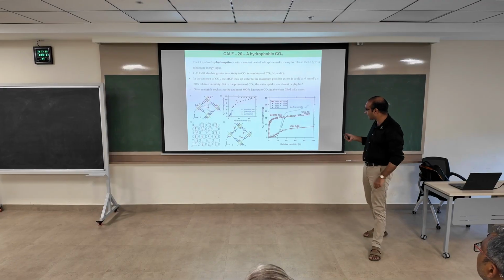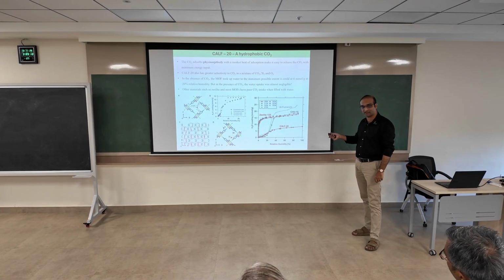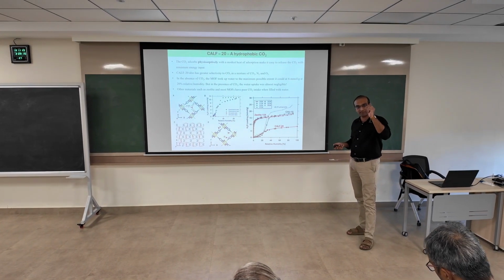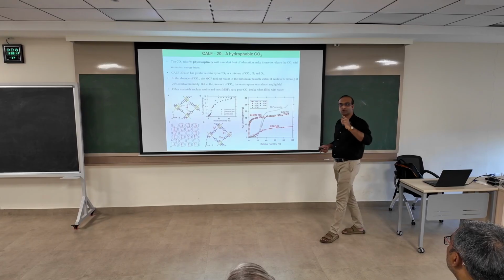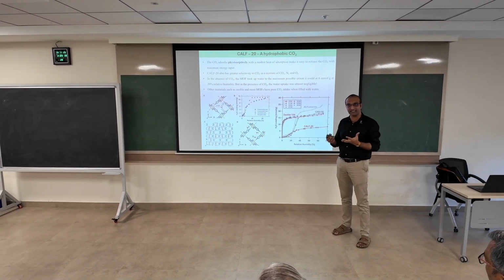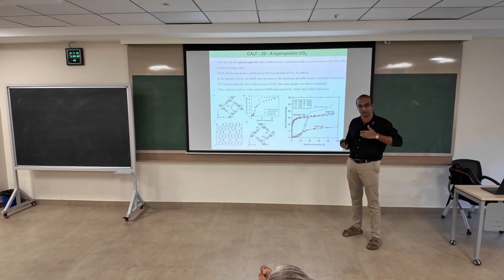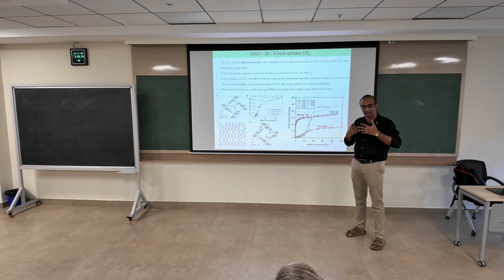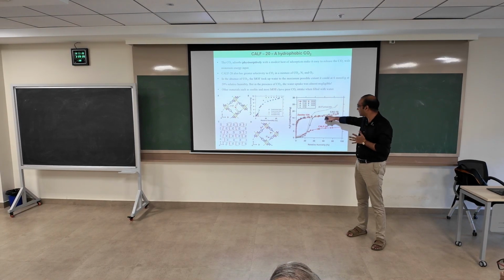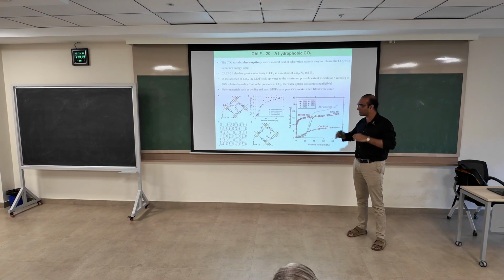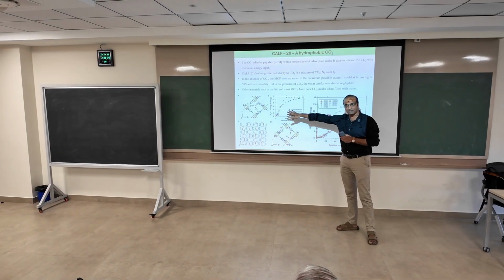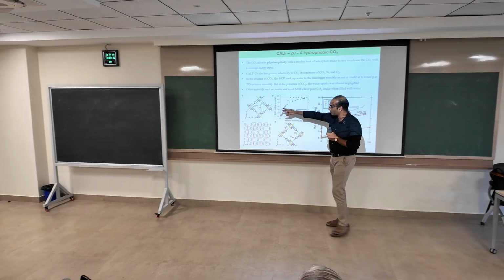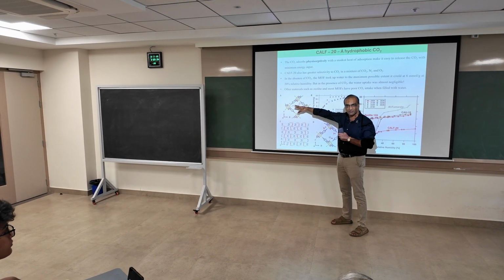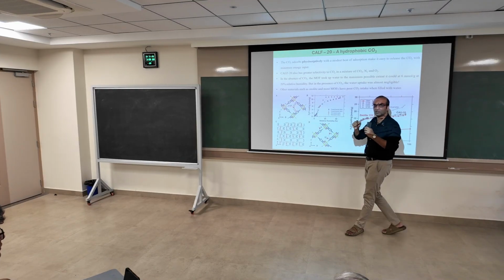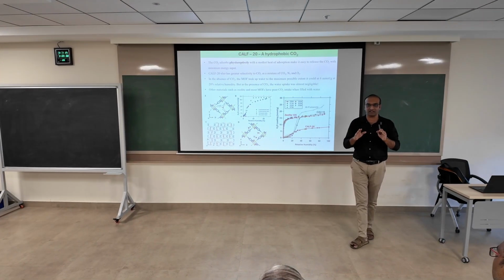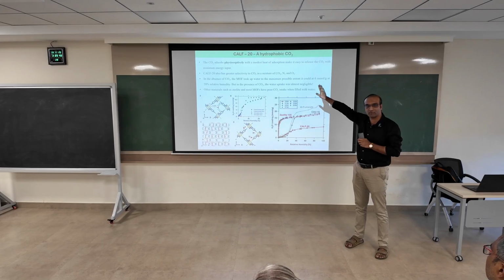Most of these other MOFs, like CAU-10, Al fumarate, and zeolite 13X, have chemical adsorption of the CO2. So you capture the CO2, but then you have to heat it at say 200 or 300 degrees Celsius to release the CO2 again, because there's a strong chemical interaction between the bonds of that particular material and the CO2. Here it's not like that. It's more like a weak interaction. It's right at the pore. It's not bound to any of these atoms. There's no strong coordination. So you need a very little temperature, like within 100 degrees Celsius or something, and you can release the CO2 back.